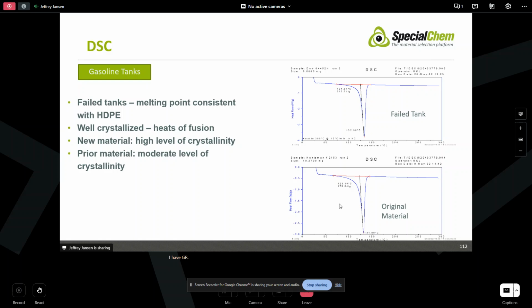Then we ran some DSC, and we found that the failed tanks had a melting point that was consistent with high density polyethylene. They were well crystallized. These are the second heating run, so they had good heat of fusion. What we did find out, however, is that these are not drop-in. The new material had a relatively high level of crystallinity.